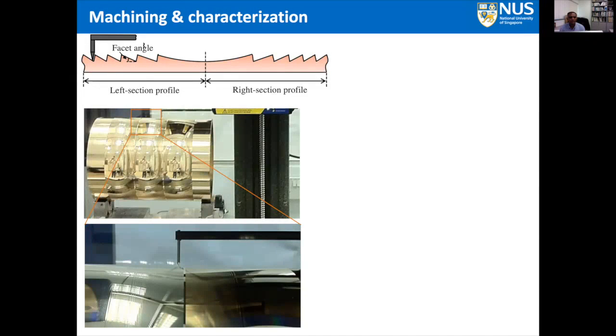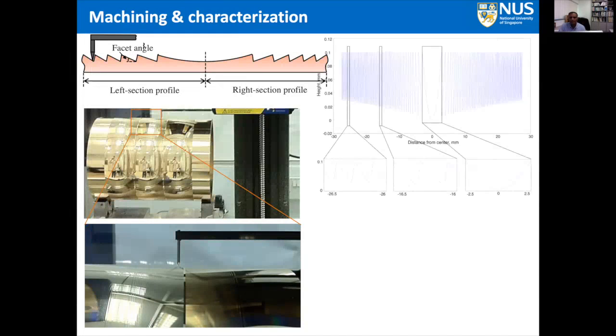Primarily, we have to measure the left section of the profile and the right section of the profile, and that is what is actually shown in this particular image here, where you see the left section of the profile having features like this, observed at the bottom, where the extreme left is very sharp, and as it progresses inside, the angle is deeper, and you can see the central feature, which is a spherical lens being produced. And of course, we use the stylus profilometer in order to measure this.